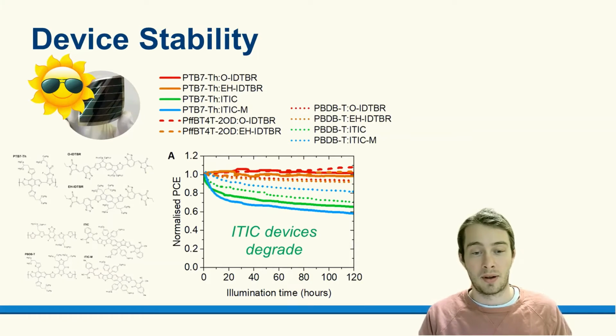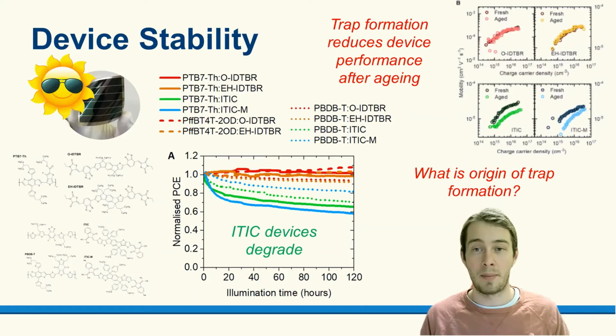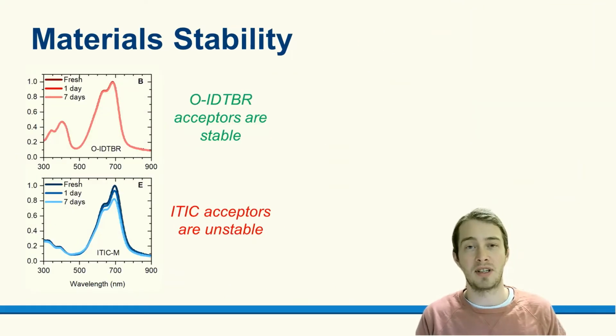And to understand why this is happening, we do some more electrical characterization and find that there's trap formation in the device as we age it under solar illumination. And so what we want to know is, why is there trap formation in the ITIC devices and not the IDTBR devices? So to investigate this in a bit more detail, we look at the stability of the individual materials themselves. And so if we illuminate the materials under one sun and then look at the absorption spectra after degradation, we can see that the IDTBR doesn't change at all, which means that these materials are very photostable. Whereas if we look at the ITIC acceptors, we see this bleaching of the absorption, which is telling us that there is some kind of degradation happening at a molecular level.